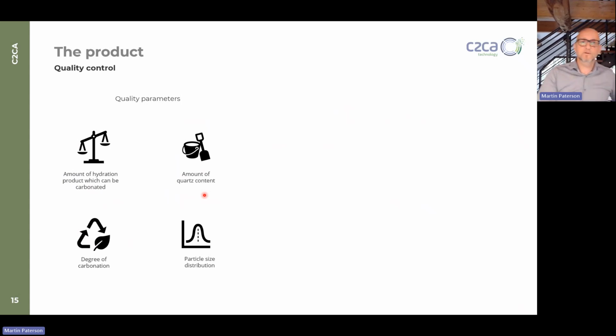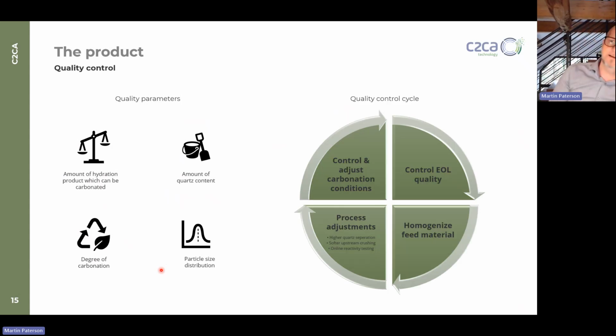Quality control is mandatory, and the quality parameters interesting for us are the yield of the reactive, or let's say amorphous, material which we can make reactive afterwards. So we currently measure and test how much of the recycled cement paste we can get out of the waste concrete. We need to measure and react on the amount of quartz within the material, as this cannot be activated afterwards. The particle size distribution is very important. And then finally, after the carbonation has been conducted, we need to measure the degree of carbonation.